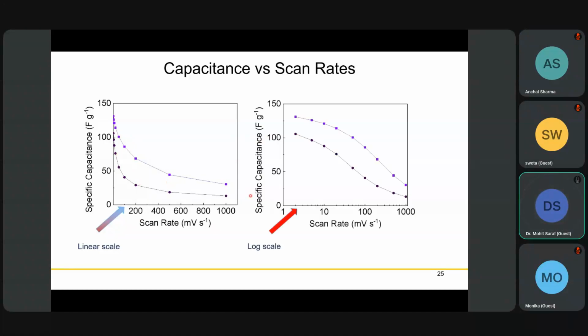When you convert the x-axis to the log scale, you will actually see that the capacitance decay is not very fast. At 100 millivolt per second you still get a decent capacitance. The same data is there, but without the log scale it looks like a very fast decay. So it is also very important to put the correct log scale on your axis to present your data in a better way.